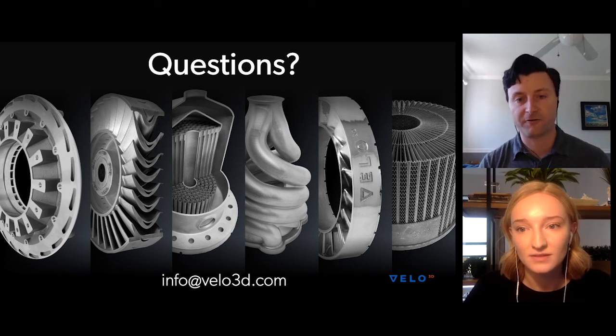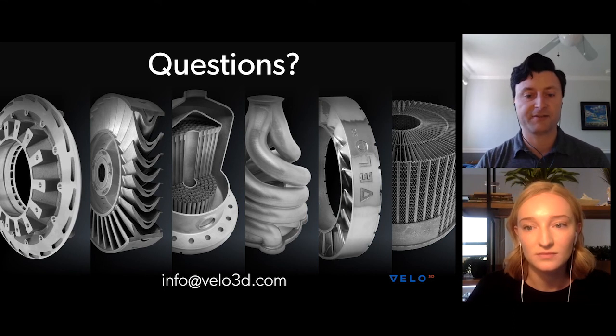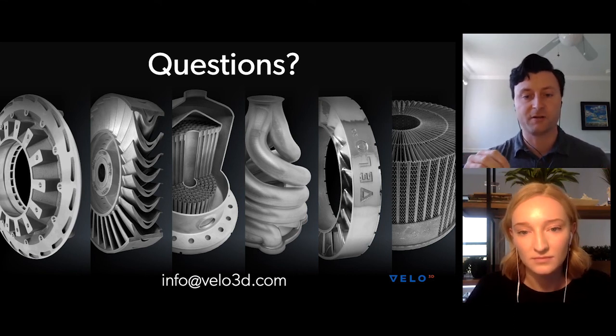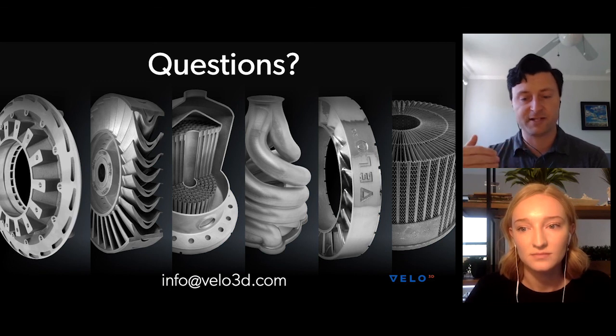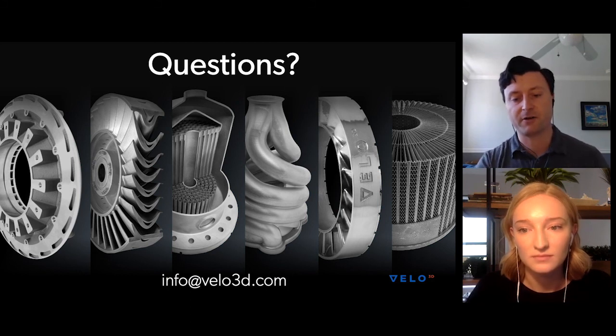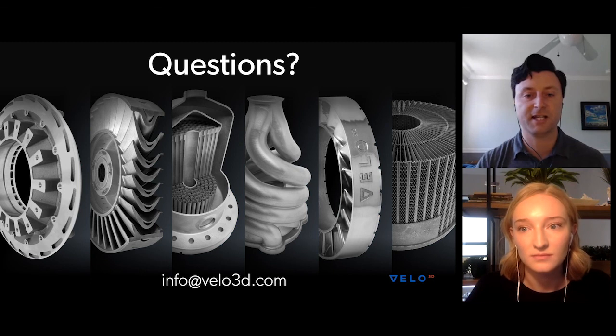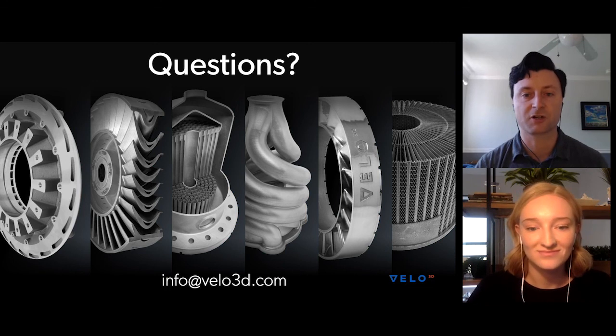So when we talk about our free-floating build capabilities, one of the really important things there is that we're starting without any consideration of what's below the part. So lately I've seen some support-free parts where really they're printing the part kind of inside a holster. And the reason they have to do that is that the recoater applies force. And so there's no way to really build a truly free-floating part in other systems. Whereas with our system, the ability to lay down powder in a very consistent bed without applying any force gives you the ability to print low angles, to print free-floating parts, to print very high aspect ratio parts, such as in heat exchangers. And it's really kind of a true differentiator in terms of system architecture.